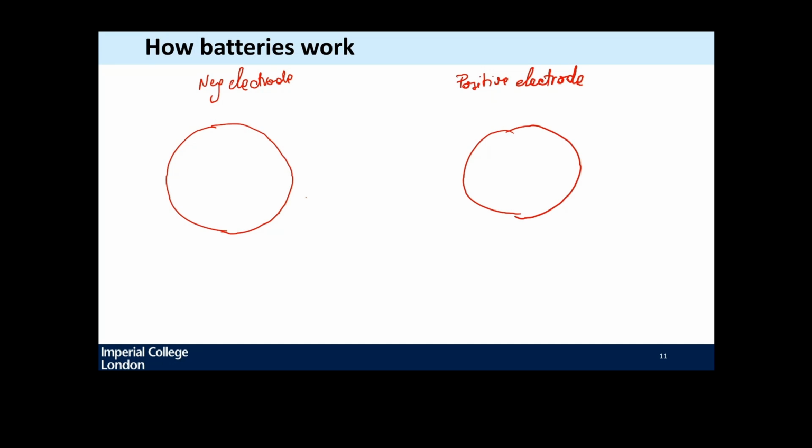And the negative electrode is a material that was chosen because its energy state is such that when it's in this particular electrolyte, it wants to release, it's energetically favorable to release lithium atoms into lithium ions. And for this reaction to occur, this is a plus, it's also giving out an electron. So this is in principle an electrochemical reaction happening between an ion and an electrode.